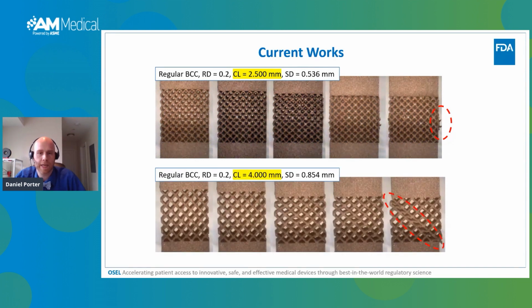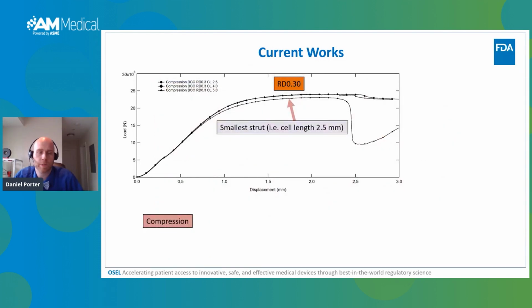So we've got some Ti alloy samples that we're testing in the as-printed condition. The smallest strut diameters show a lot of splintering, and then as we increase the strut diameters, you get this shear failure mode that you see a lot in the literature. And here are some load displacement graphs. Keep in mind, this is an N of 1; we haven't tested multiple. You generally see the same performance trend, except it's not as amplified as we saw on the nylon. We haven't simulated these; these are all experimental, but the smaller strut diameter performed under the two larger strut diameters at the relative density of 0.3 in compression.